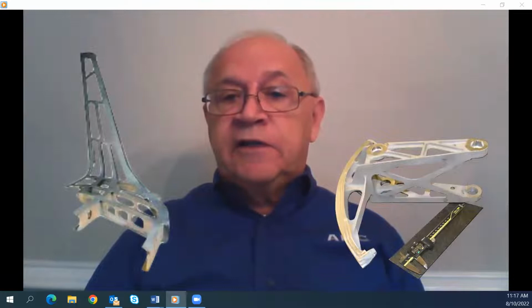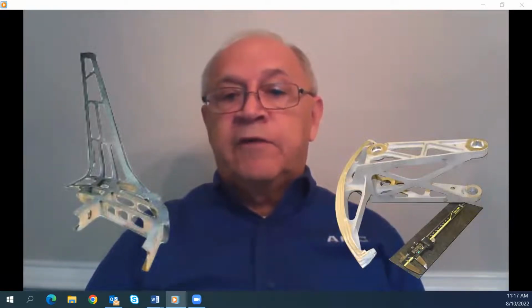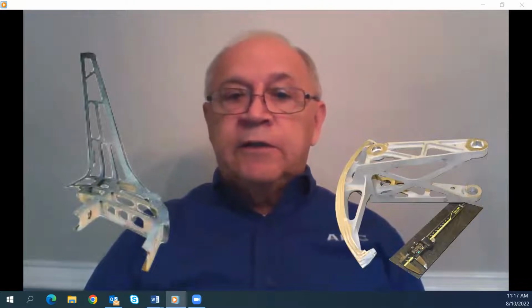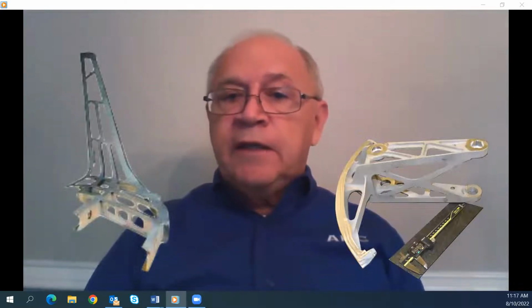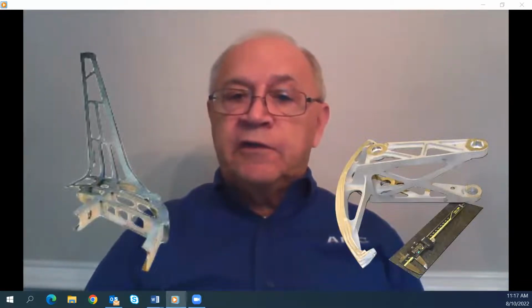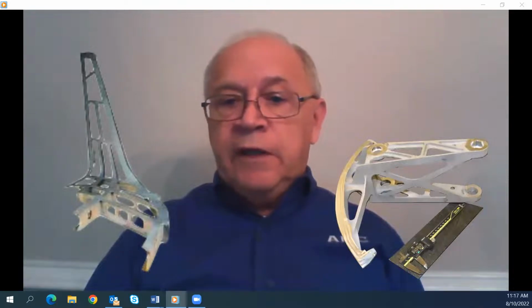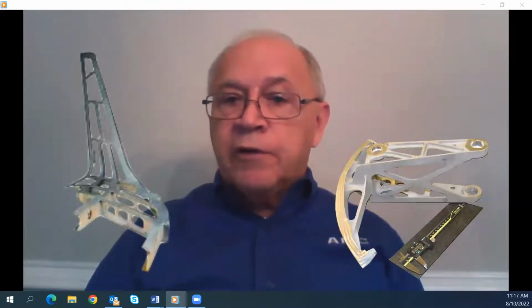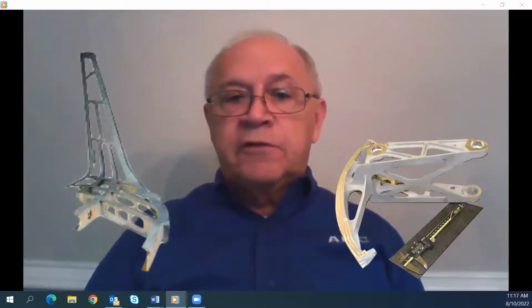So an important question for a machine shop is this: is there in close proximity a capable solution heat treater to assist in the back and forth softening and straightening process? Machining cuts in castings are less significant. In other words, they remove less volume of material. So typically, the straightening during machining steps is not required. So metal casters making thin-walled castings in these alloys typically have heat treatment in their finishing facility. And they also have either in-house machining or local machine shop partners. So the process is much easier to accomplish.